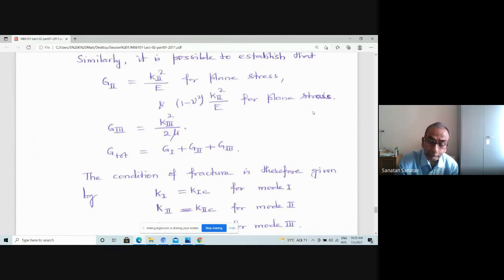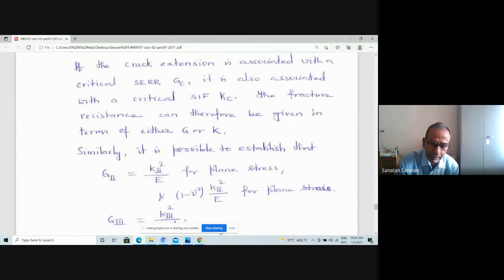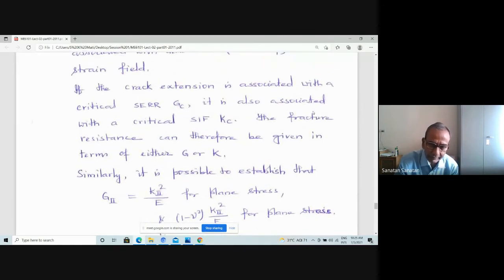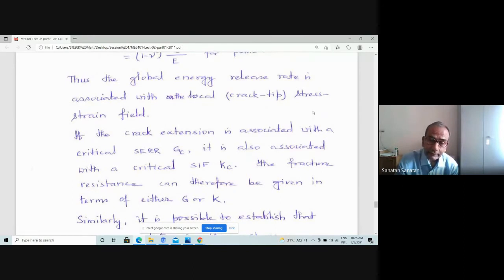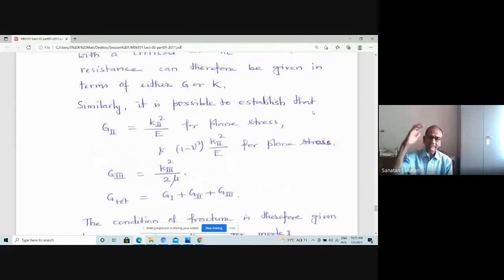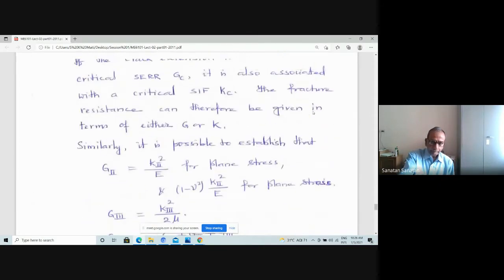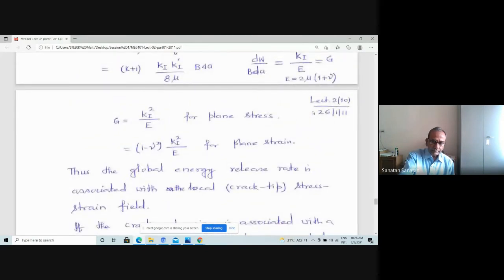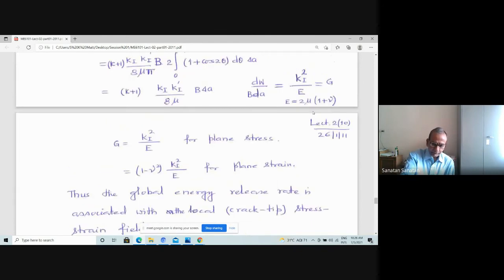And therefore, you see that for all the three modes of crack extension, that is tensile mode, shear mode, and torsion mode, for each of the cases, Griffith theory was related to Irwin's theory. Like here, for all the three modes, he gave the final position that for mode 1, this G subscript 1 is related to K subscript 1 at the point of onset of crack extension. This is therefore G1 reaching a critical value, and K1C is a critical condition for crack extension.